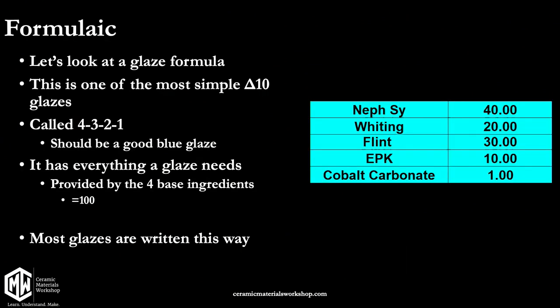To understand how colorants work in glaze chemistry, we have to talk about how glaze chemistry really works. It starts with a formula. Here's a very basic glaze formula called 4321 — pretty much the simplest Cone 10 glaze you can make. It makes a very nice glossy glaze at Cone 10. The formula is written as: nepheline syenite at 40%, whiting at 20%, flint at 30%, EPK at 10%, and cobalt carbonate at 1%. You'll find glaze formulas written like this on websites like glazy.org.